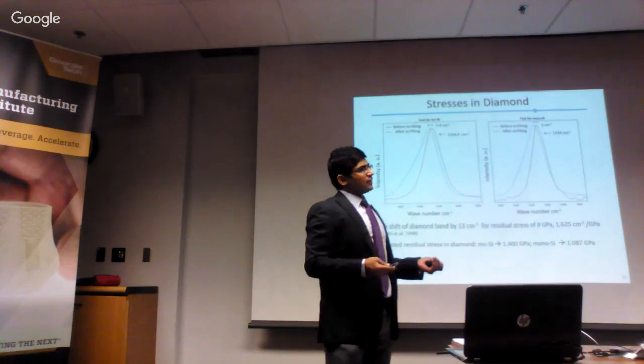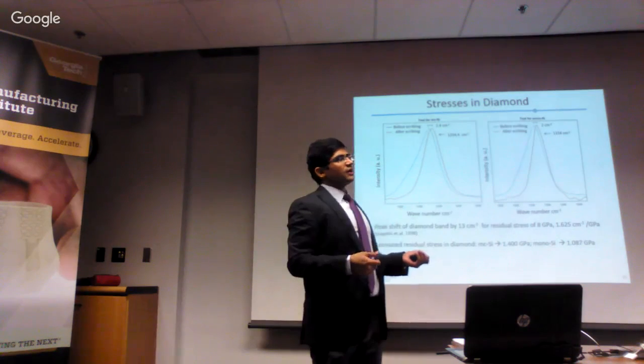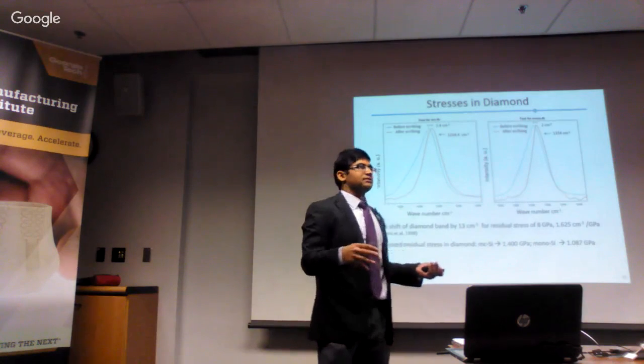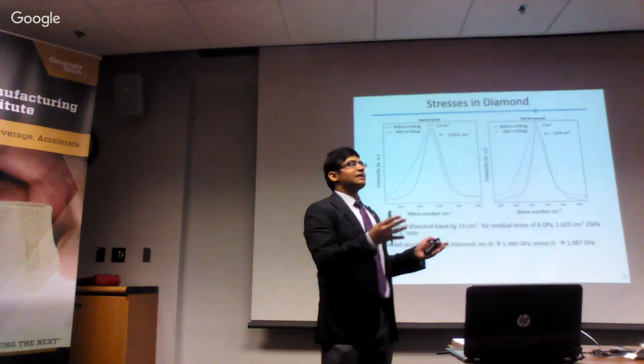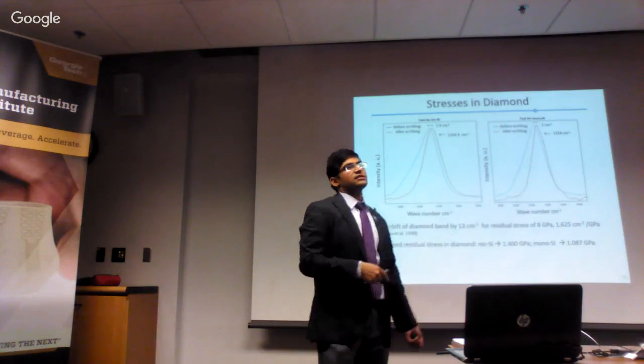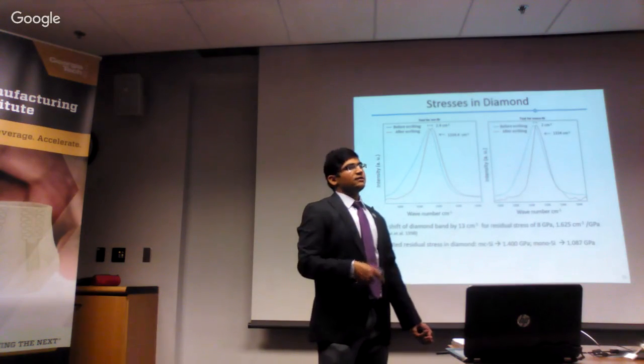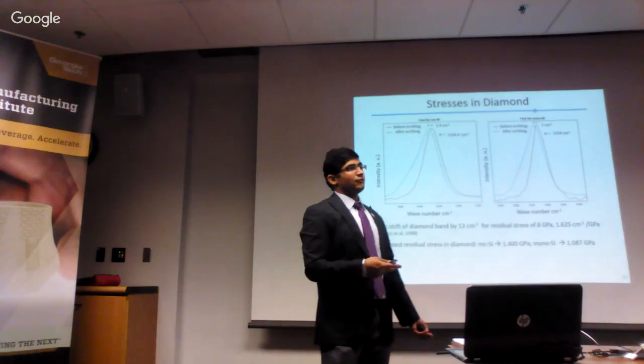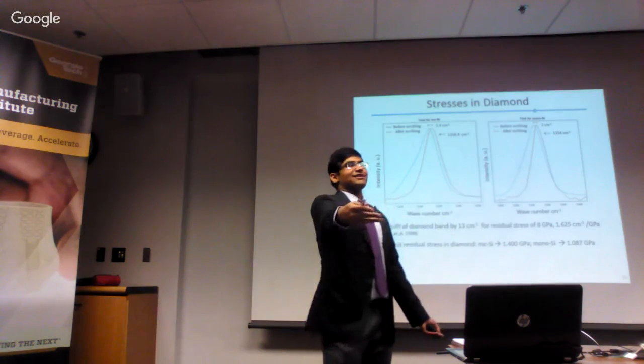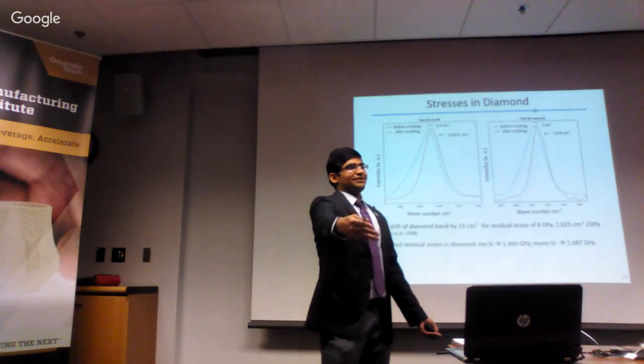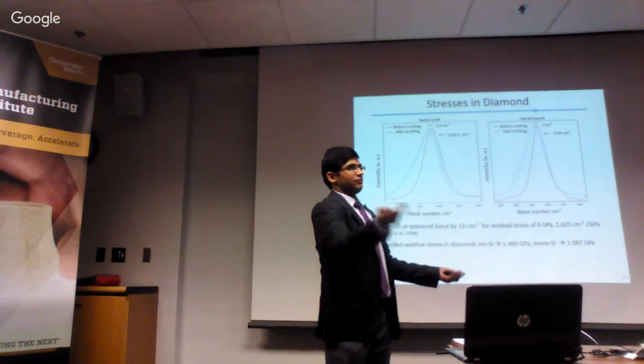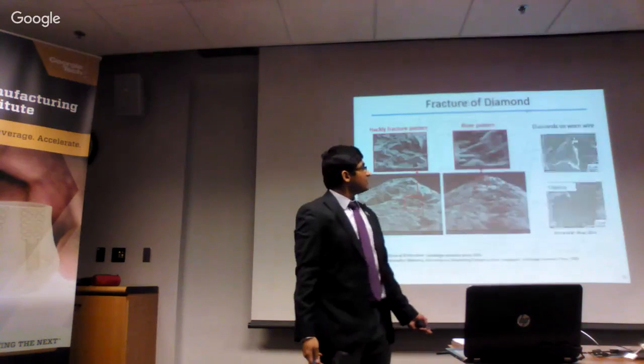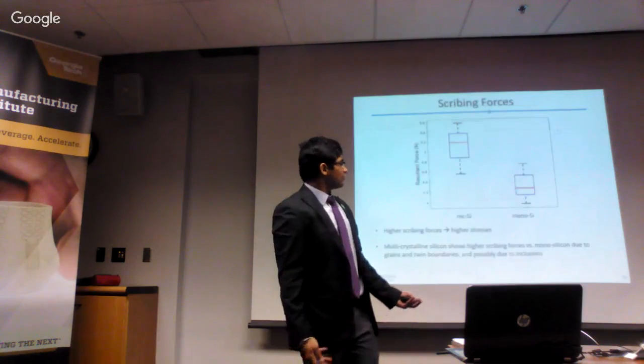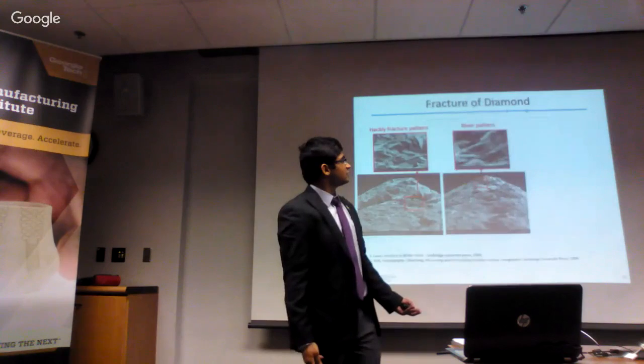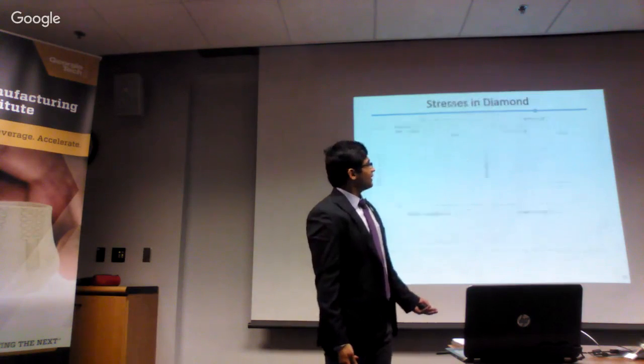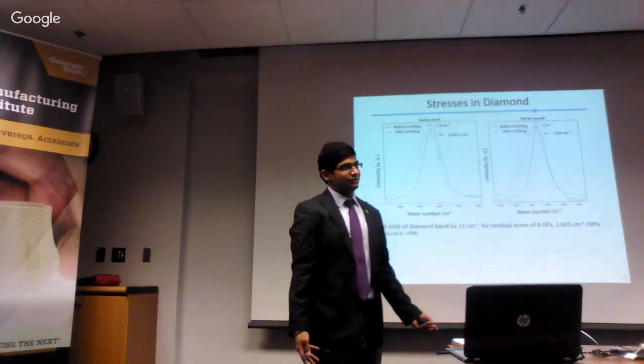So how do you believe it's significant? I believe it's significant because this was done over many measurements and then taken the average and standard deviation. We found it to be consistently giving higher for the multi-crystalline silicon case compared to monocrystalline silicon. And it's consistent with the story we have that the forces are higher and it is expected to create higher stresses. So it validated what we are seeing very readily earlier. Right? And it also validated the radius of curvature change was more. So it was very consistent with the story which we found.